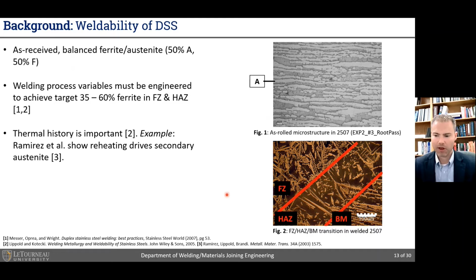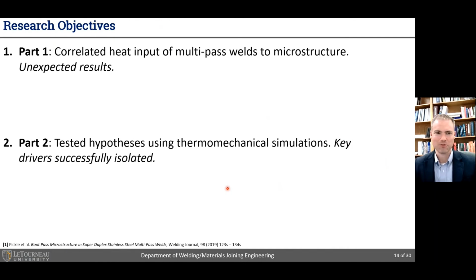So with this as a background, let me go ahead and state what we were trying to do in this work. So we had two major research objectives. The first was a kind of exploratory study where we were looking at correlating heat input of multi-pass welds to microstructure. And in so doing, we got some unexpected results. And that drove the second phase of the work, where we tried to test some hypothesized mechanisms. And we found that the thermomechanical simulations, coupled with welding, were really key and helpful in identifying the key drivers and isolating those.